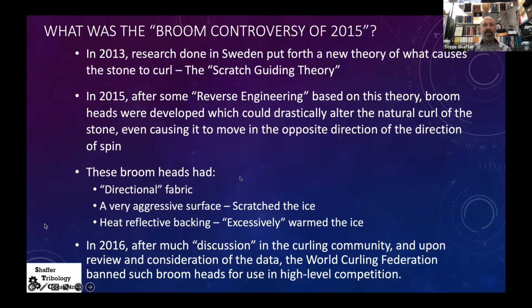So these broom heads had a sort of directional fabric, a very aggressive surface, which could scratch the ice. And they also had a heat reflective backing behind this fabric, which could excessively warm the ice. So they were trying to soften it and scratch it, and that would affect the direction of curl much more so than any natural thing. So it became sort of unfair. There was a lot of discussion in the curling community, and there is a World Curling Federation. And upon review and consideration of the data, good for them, they banned such broom heads for use in high-level competition. They wanted the athletes to determine the outcome and not the equipment.